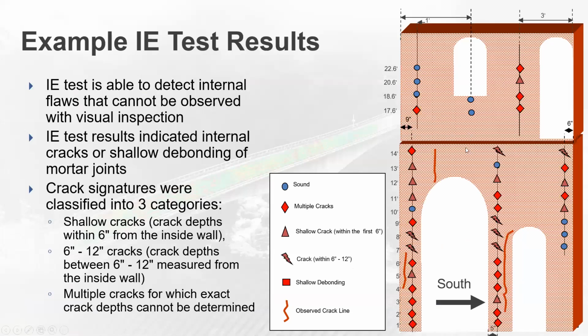So we plotted the results up on a grid. And you can see a scale on the right and a legend. It says sound, multiple cracks, shallow cracks in the first 6 inches, cracks at 6 to 12 inches deep, shallow debonding, and plotted the observed crack lines. So this sketch shows those results.